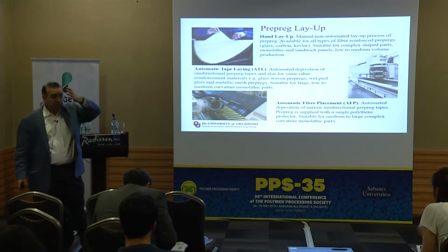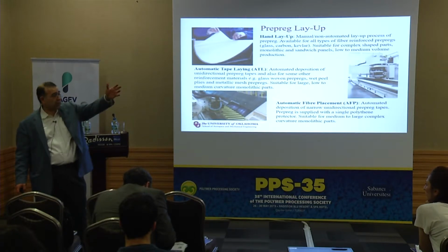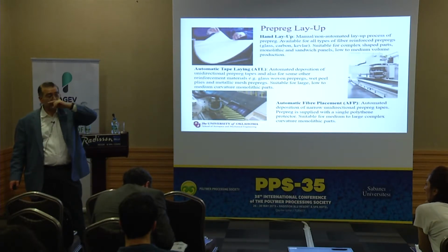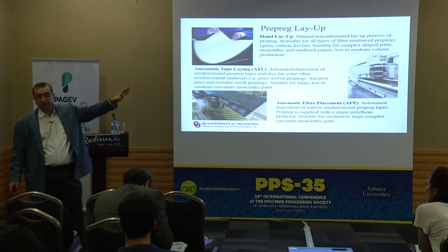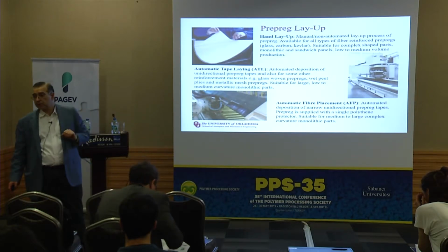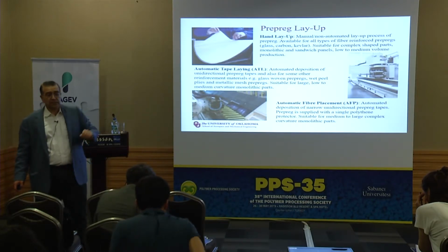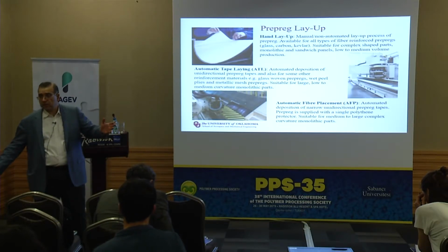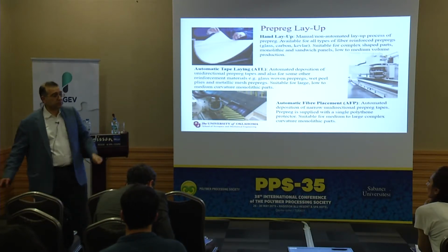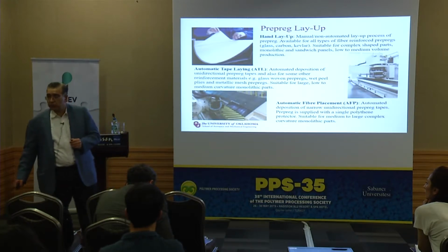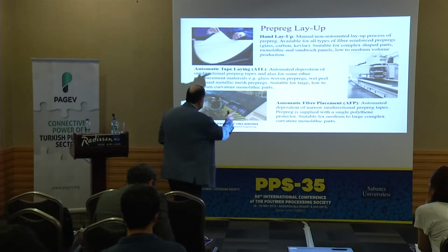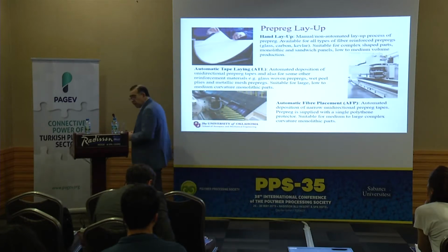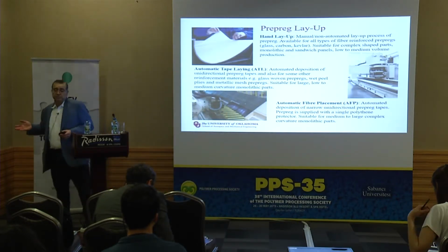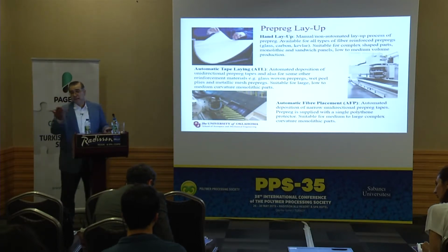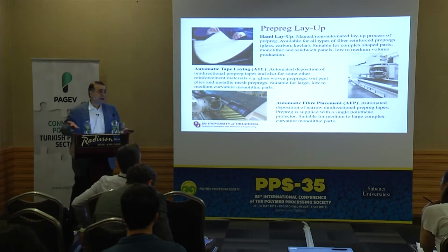Now, you might say, well, I have like 2% or 5% voids. What are their effects? Well, 1,000 megapascal flexural strength will go down to 700. 600 megapascal may go down to 300. So anywhere from 30% to 50% reduction because of 5–10% voids. So the void is a big deal in composites, especially in thermosetting laminates. And many people do not really understand or appreciate this. They never cut their sample, they never looked at their product under the microscope, and they have a bunch of voids.